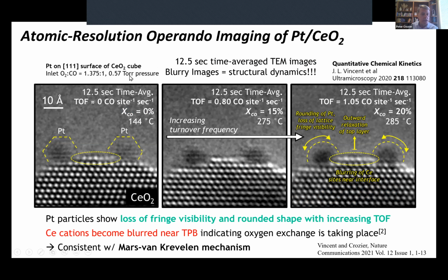There's a lot in this slide here. And we actually measure chemical kinetics quantitatively inside the ETEM. And I don't have time to talk about how we do that. It involves using electron energy loss spectroscopy and also a lot of finite element analysis of heat and mass transport. If you're interested, we published the process in this Ultramicroscopy paper here. But what I want you to look at is, here are platinum nanoparticles, and here's the ceria support. In the nanoparticle, the platinum atoms are in black dot focus, the ceria is in white dot focus.